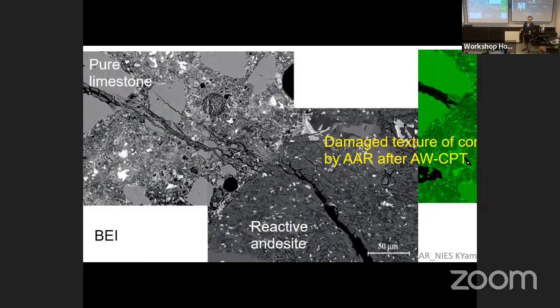Aggregate is porous enough for solution to penetrate into the aggregate from the environment. In the solution, hydroxide ion and the same molar amount of sodium ion exist. So they simultaneously penetrate and reach reactive silica. Then silica dissolving means the Si-O-Si bond changes to SiOH and SiOH, so one OH is exchanged by sodium. So SiONa, such material is formed, with expansion, with a volume increase.